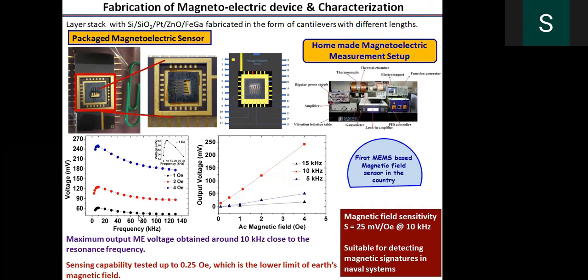We have tried to measure the variation of output voltage with respect to frequency for different fields. We could see that around the resonance frequency, as you know, the resonance frequency shows a maximum vibration. Around the resonance frequency, the output voltage has been found to be extremely high. This shows the variation of the output voltage with the AC magnetic field, and we could see the response is very good even up to 1 oersted.